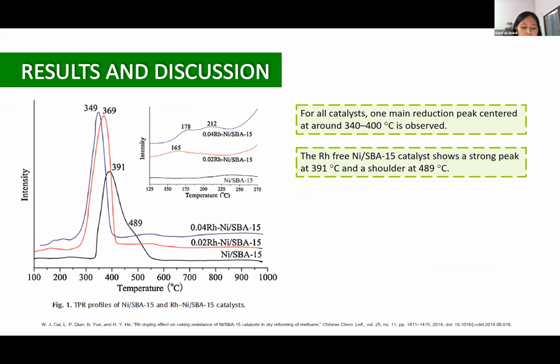In figure 1, for all catalysts, one main reduction peak centered at around 340 to 400 degrees Celsius is observed, which can be explained by the reduction of supported nickel oxide species with different interaction with the support surface. The rhodium-free nickel on SBA-15 catalyst has a strong peak at 391 and a shoulder at 489 degrees Celsius. This means an uneven distribution of nickel oxide species interacting differently with the support. The main peak is shifted to 369 degrees Celsius in 0.02 rhodium nickel on SBA-15, indicating that the reduction of nickel oxide is promoted in the presence of the noble metal.